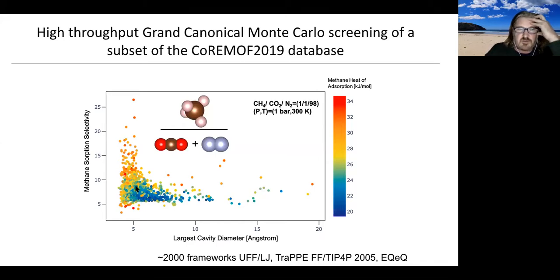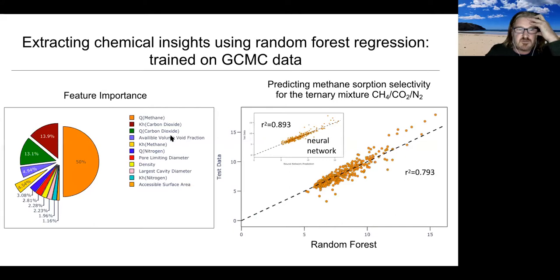So we'd obviously like to go beyond that. Tom Pope, who did these calculations, has been using machine learning to try and identify good descriptors for this particular process. We see here the outcome of a random forest machine learning fit. It's a reasonable R-squared value, and this gives us some chemical insight and allows us to identify the important features which are responsible for the high selectivity for methane.